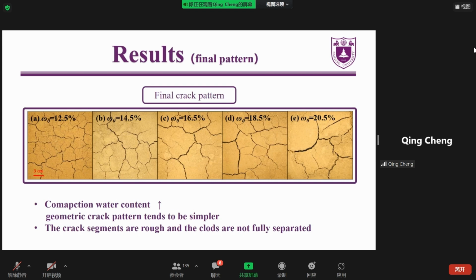In previous studies investigating desiccation cracking of slurry samples, the researchers got a common view that the crack segments are smooth and the soil surface is split into separate clods by the crack network. However, in our study, we find that the crack segments are rough and the clods of the compacted soil samples are not fully separated. This can be attributed to the homogeneous structure of the slurry samples and the heterogeneous structure of the compacted soil samples.